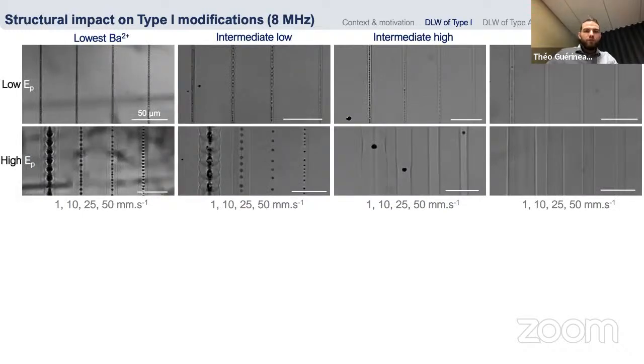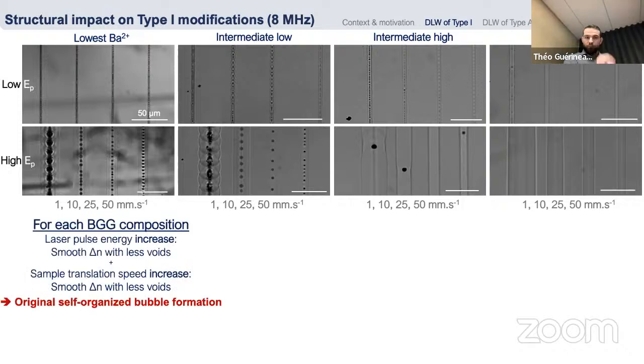So from the picture from the left to the right, you see 4 glasses with an increase of the concentration of barium, and from the top to the bottom, you see an increase of the energy pulse. For each picture, you have 4 waveguides inscribed at, respectively, 1, 10, 25, and 50 millimeter per second. So for each BGG composition, you increase either the laser pulse energy or the sample translation speed.